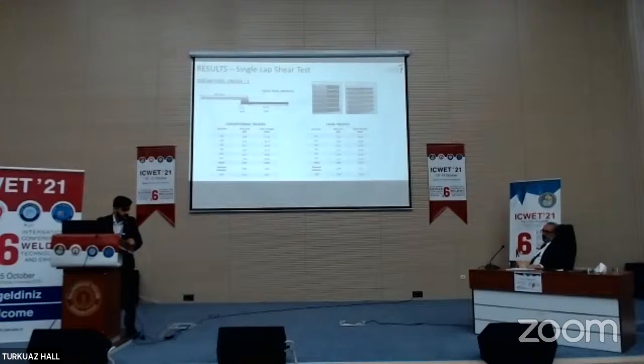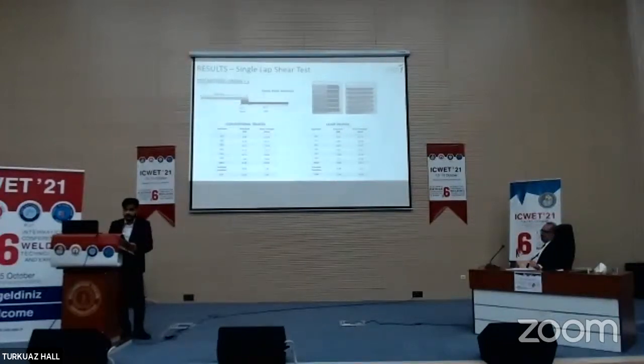when we compare the results, first of all, we apply the same procedure. We apply the test to the specimens that are treated in the conventional way. As I said before, for titanium alloy surfaces, chemical treatment was used, and for thermoplastic materials, grit blasting is the favorable process technique, and we applied the single lap shear test, and we obtained nearly 25 megapascal. And we also applied the test for laser treated specimens, and we obtained nearly 23 megapascal.